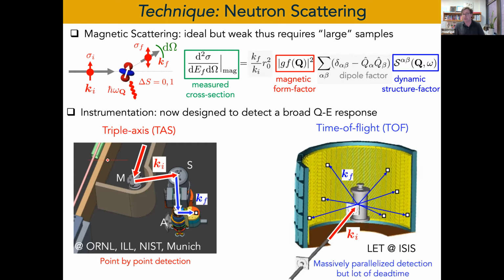And the advantage of this technique is that instead of having one detector, we have millions of, we don't have millions of detectors, but we have millions of pixels that surround our materials. And this allows to massively parallelize the detection of the neutrons that are scattered from the sample. So the idea here is that every neutron that is scattered from the sample has to be detected, because it contains information about the sample.